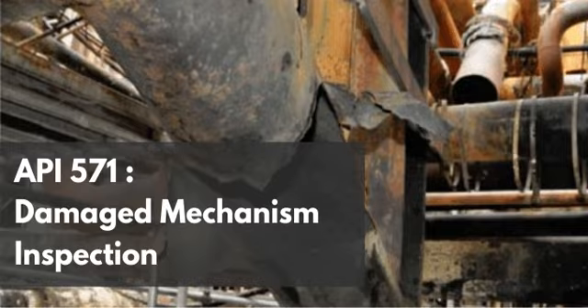Does it happen overnight? Not quite overnight, no. The source data details the time at temperature kinetics. It says that carbon initially diffuses into the component at a very high rate, which then tapers off as the depth of carburization increases into the wall. This is a classic diffusion kinetic curve, and it's crucial to understand why this tapering occurs.